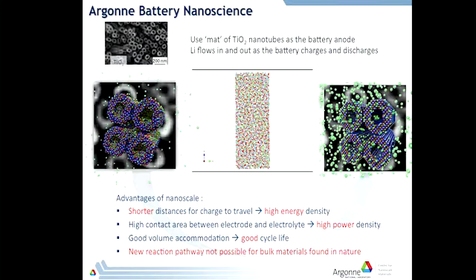Okay, I'll play again. If you look at this, this is the amorphous structure here, so completely random atom arrangement. And what's being simulated here is what happens when the lithium goes into that material. And you can see that as the simulation progresses, you start to form these lines. And what you finally end up with is a perfectly ordered crystal structure of lithium, titanium, oxygen. And that's what's shown in the simulation here. You're starting with the amorphous random structure, and here it's now perfectly crystalline.